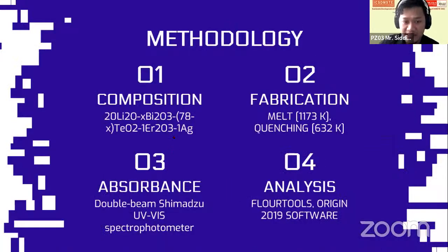So this is the methodology. So this is my composition. We increase bismuth. Bismuth is a big atom, so it will cause disorderness in our glass network. And then we fabricate our glass by using the melt quenching method. And then we do the measurement for the optical absorption data by using the spectrophotometer. From the optical absorption data, we analyze it by using the Flourtools and also Origin 2019 software.